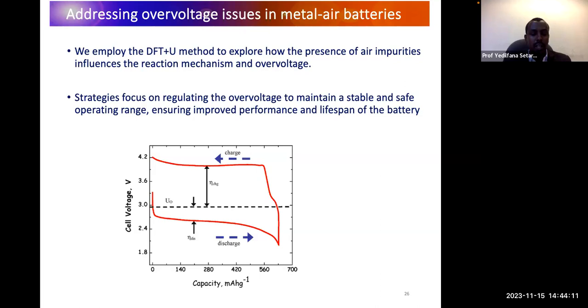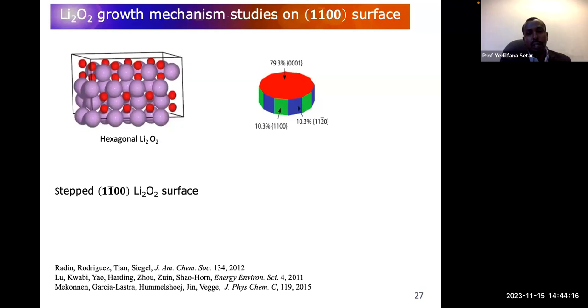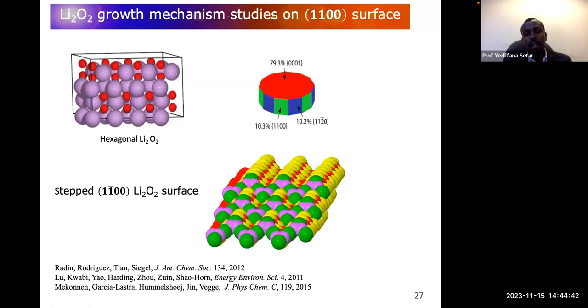I will maybe talk about the interface engineering mechanism to reduce the overvoltage issue in this case. I already informed you that it's not intercalation, rather it's a growth mechanism. So we want to model the surface. We have the hexagonal lithium peroxide. From hexagonal lithium peroxide, we form a surface, and we found 11 bar 00 is the most stable and highly exposed surface in practical lithium oxygen batteries.